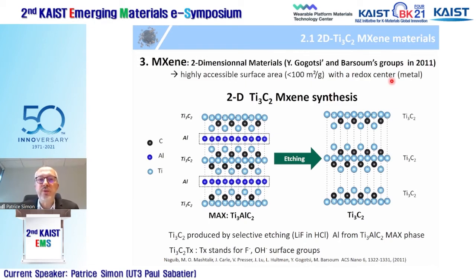So obviously these MXenes were discovered by Professor Yuri Gogotsi in 2011 at Drexel University with Michel Barsoum's group. And basically how you prepare MXenes, you start from a MAX precursor, for example Ti3AlC2, and you are going to etch this MAX precursor in fluorine-containing electrolyte, like a mixture of LiF plus HCl. And by doing that, you etch the A layer and you prepare, for instance, here, Ti3C2 MXenes.